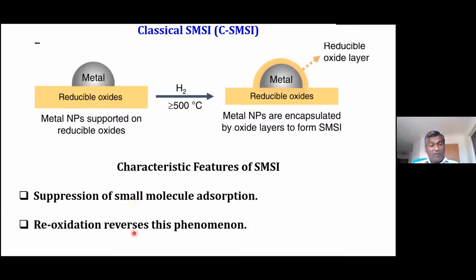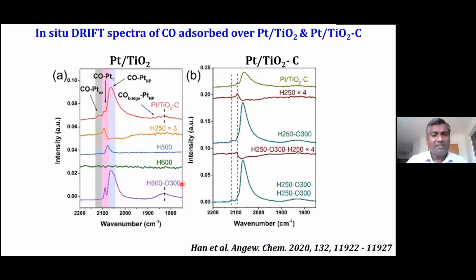And another important feature is when you calcine or oxidize this catalyst, you get the metal exposed back. So this phenomenon is completely reversible by oxidation. You can see here, this is an example reported by Tao Zhang group from Dalian. This is platinum on titania. This is CO DRIFT spectroscopy. This peak corresponds to CO adsorbed on platinum nanoparticles. You can see a huge intensity of this CO.